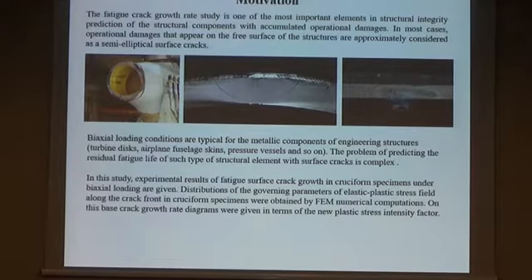So, in this study, experimental results for fatigue surface crack growth in cruciform specimens under biaxial loading are given. Distributions of governing parameters of elastic-plastic stress field along a crack front in cruciform specimens were obtained by finite element method numerical calculations. And on this base, the crack growth rate diagrams were given in terms of new plastic stress intensity factor.